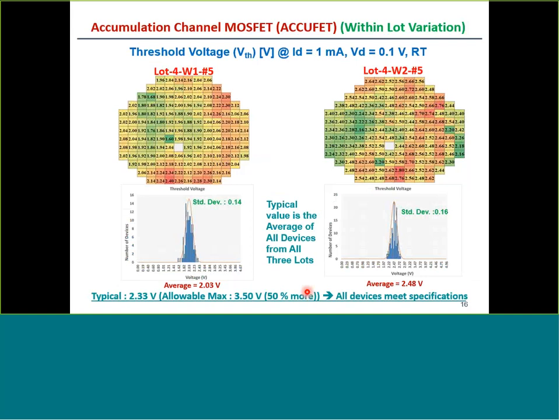The threshold voltage of our accumulation mode device is positive. There's sometimes a misunderstanding that people think accumulation mode devices are depletion mode devices. They are not. They are enhancement mode devices. They have a positive threshold voltage, as you can see here, of 2 volts average for one of the wafers and 2.48 for the other wafer. These values, again, fall within the kind of distributions we see in data sheets.